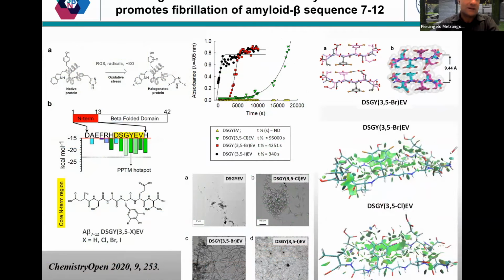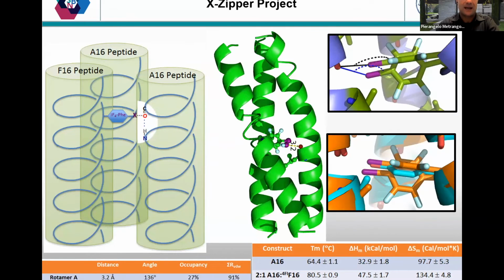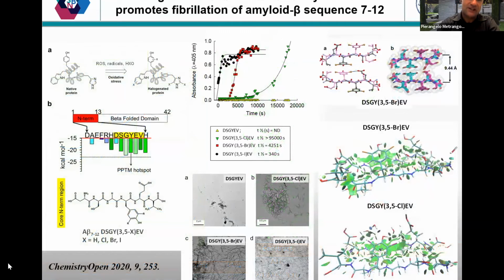Moving to the understanding of some pathologies, for example in the case of Alzheimer's, we studied this other structure. This sequence is the initial part of the beta amyloid, which is responsible for Alzheimer's disease. When you modify the tyrosine with two bromine groups, which might also happen in vivo, you get enhanced fibrillation. We were lucky to have the crystal structure where we can see the halogen bonds and also the augmented fibrillation due to the halogenation. So we believe that one of the initial steps of Alzheimer's disease can be halogenation through oxidation of these tyrosine groups, and this becomes more fibrillating.